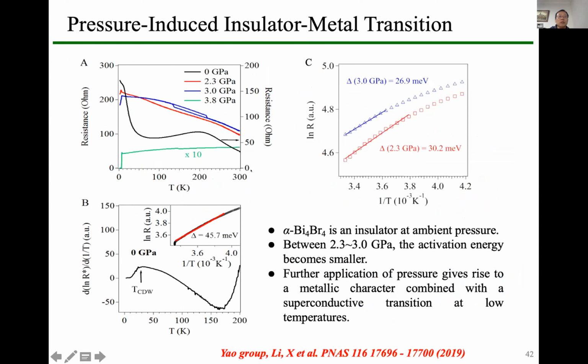Okay, we measured the transport properties under pressure, and again we found that this is a semiconductor or insulator at ambient pressure. But if we apply pressure to this material, we found that the activation energy becomes smaller, and if we further increase the pressure to 3.8 gigapascal, then this becomes a metal. So you can see the resistance decreases with decreasing temperature, and then it quickly drops to zero. So here is a superconductivity phase.